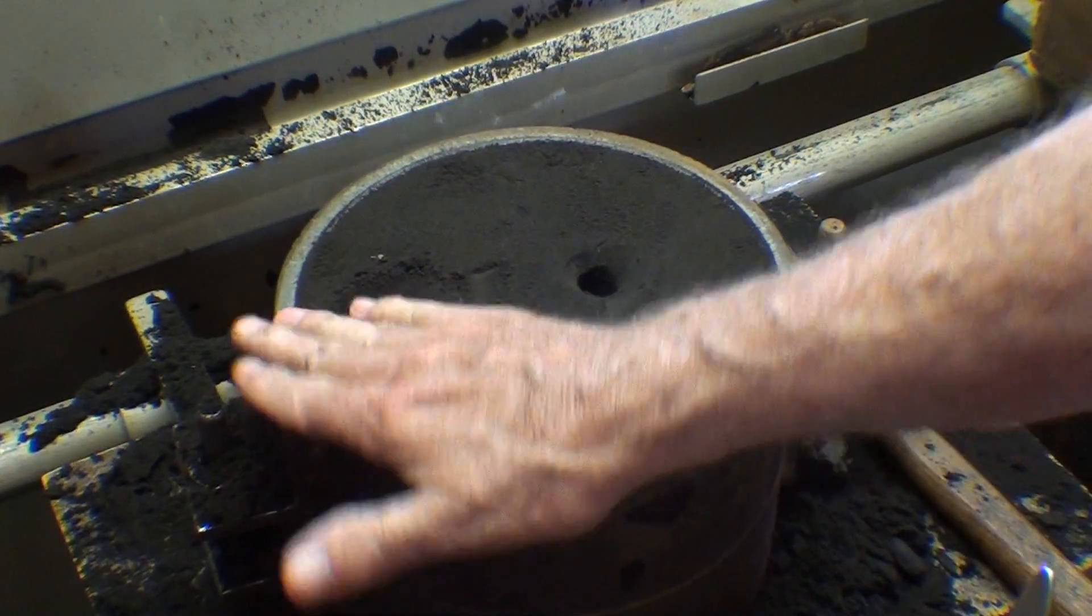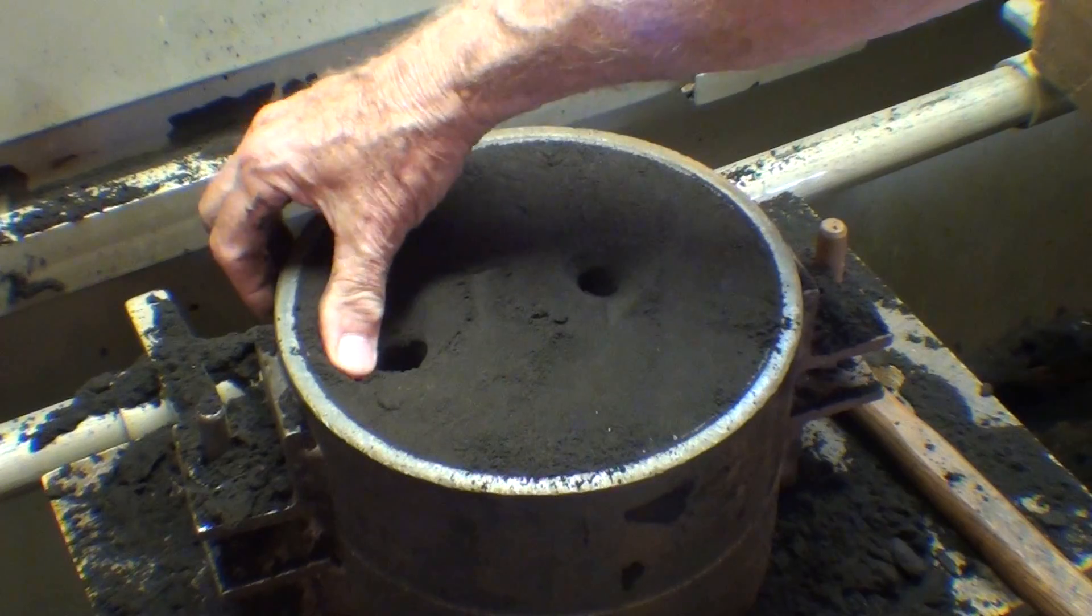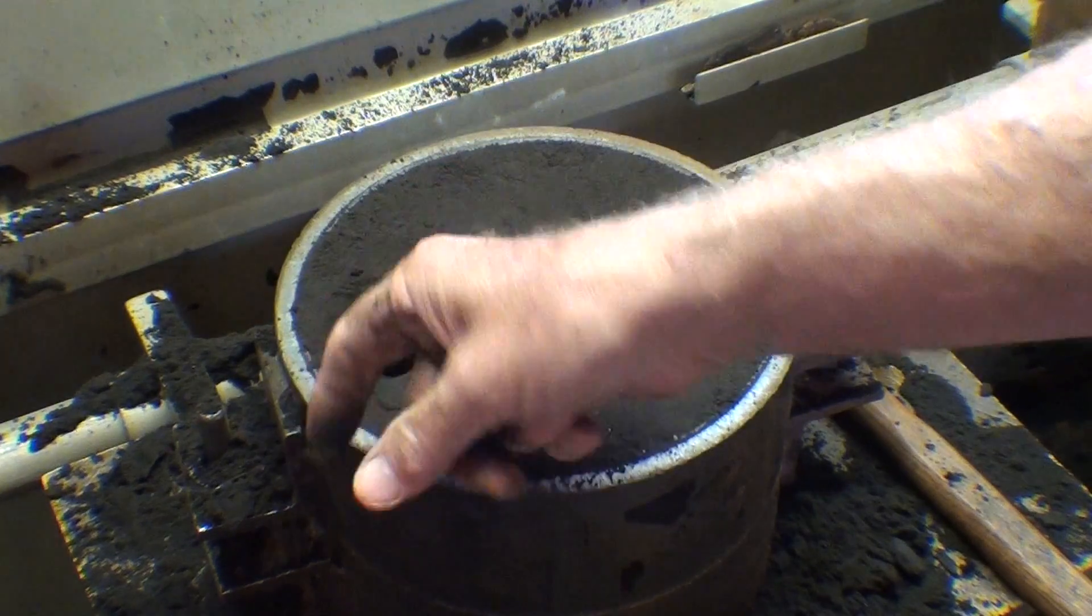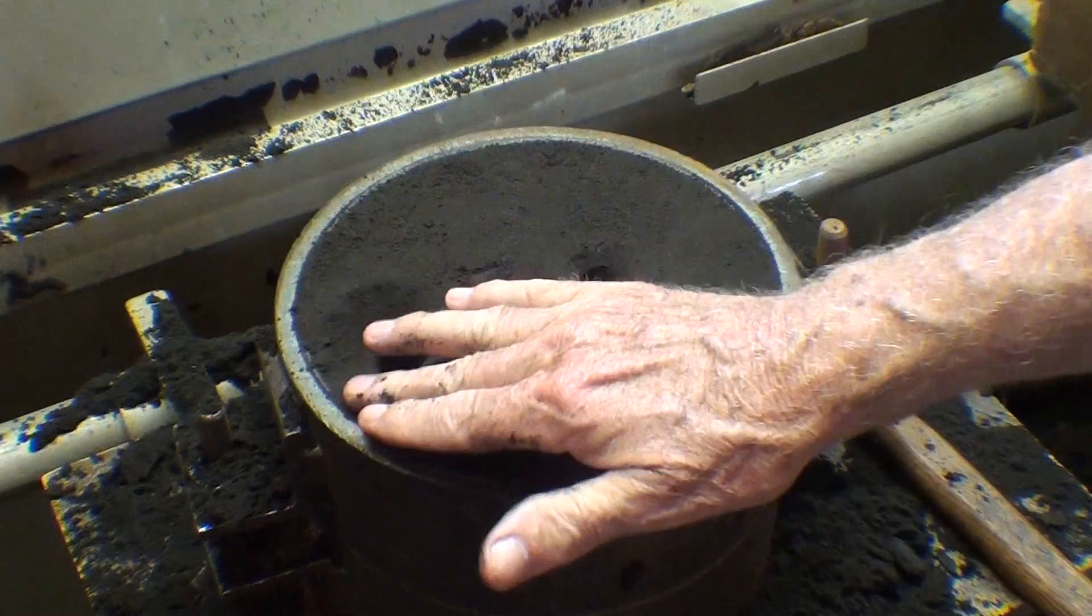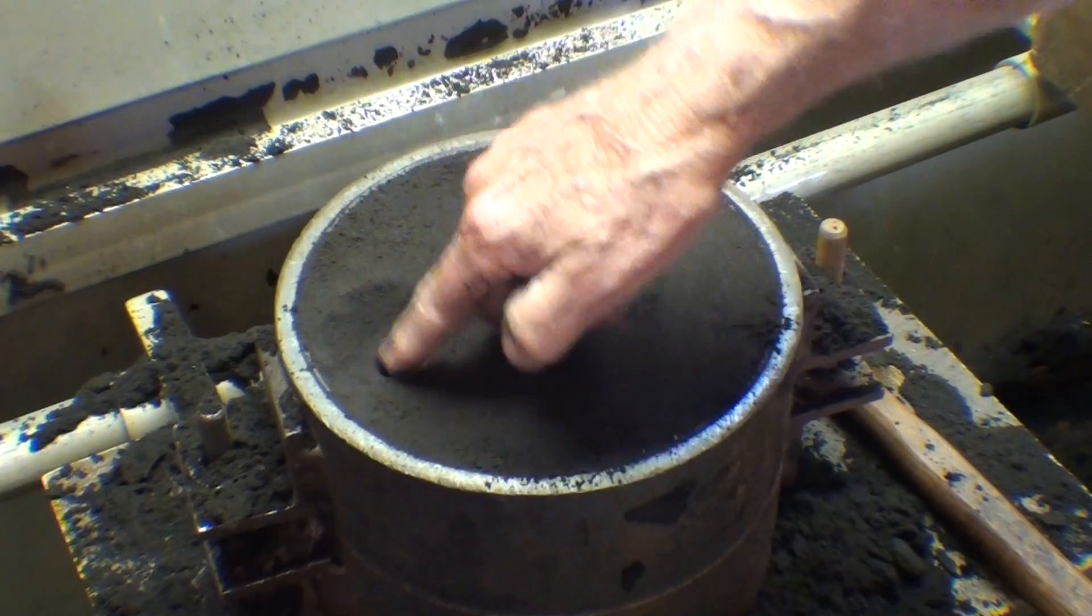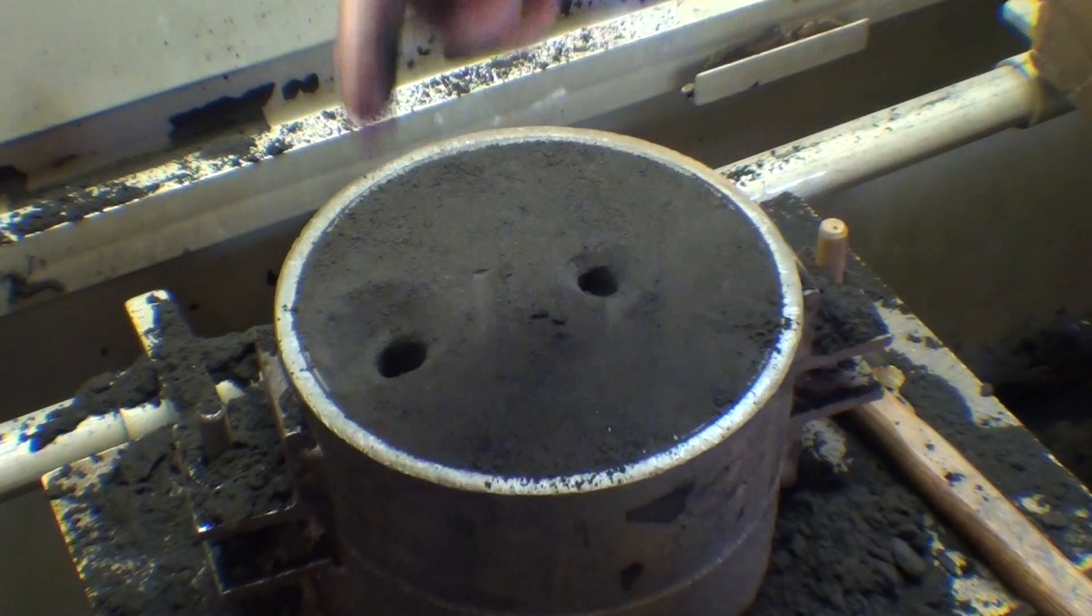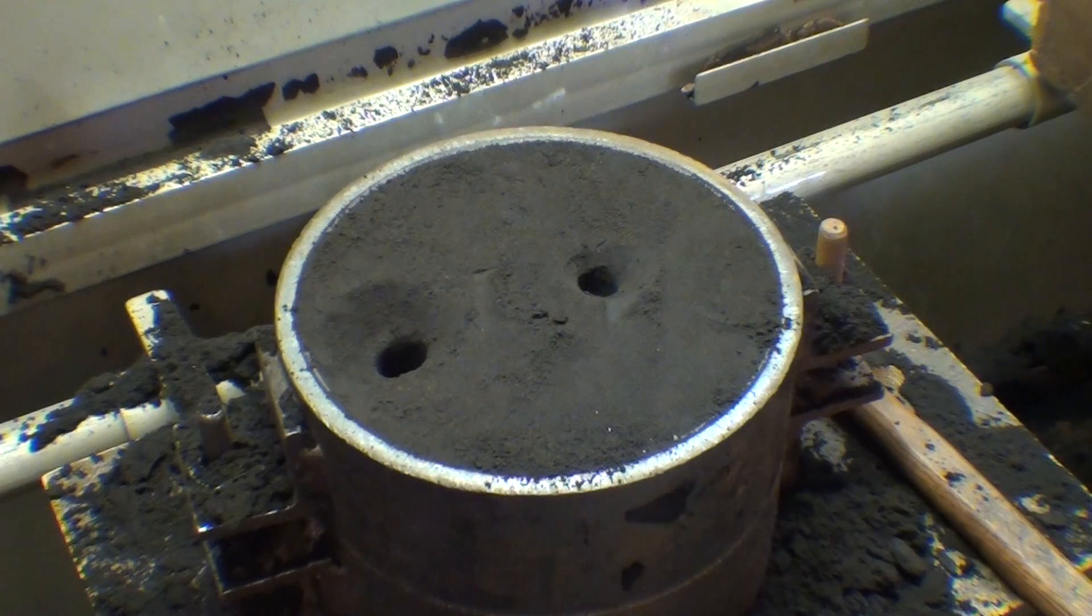I don't worry if a little bit falls in because I'm going to open it up and clean it out. And I like to tamp that down with my fingers so that no loose sand is in the area that will get washed in with the molten metal.